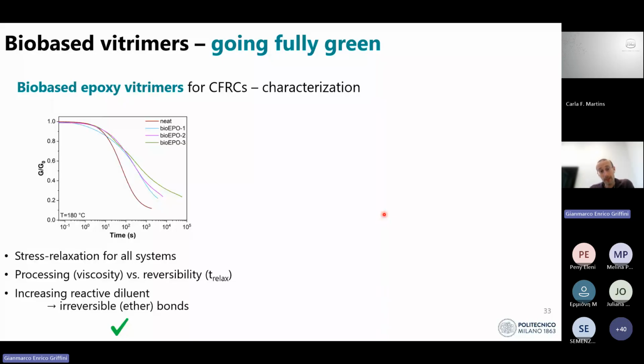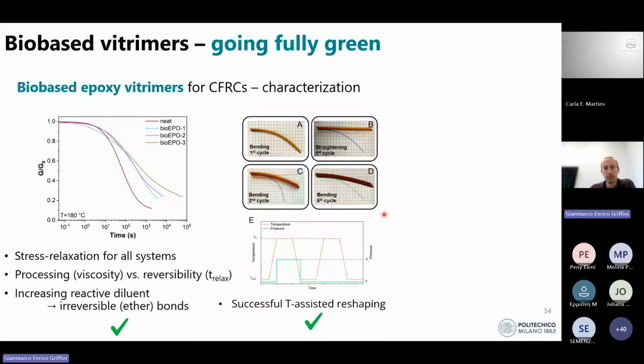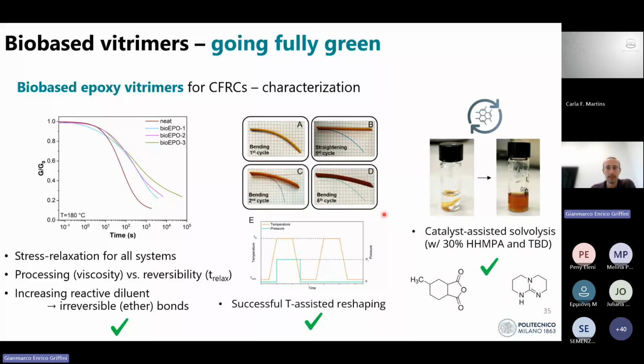The time, or increase the relaxation times. In any case, we could achieve successful temperature-assisted reshaping, as well as catalyst-assisted recycling, so a solvolysis process that was also studied in this case to achieve full dissolution.